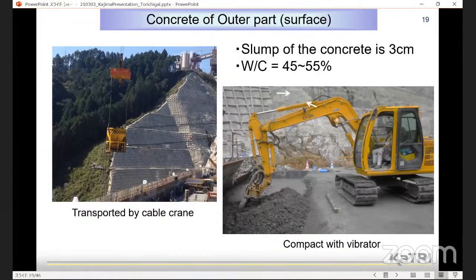And the slump of the concrete used for the outer part of the surface is 3 centimeters. The water cement ratio of the concrete is ordinarily 45 to 55%. The concrete of the outer part is transported by cable crane and compacted with a large vibrator that is attached to heavy equipment. The maximum size of the gravel is 80 millimeters.